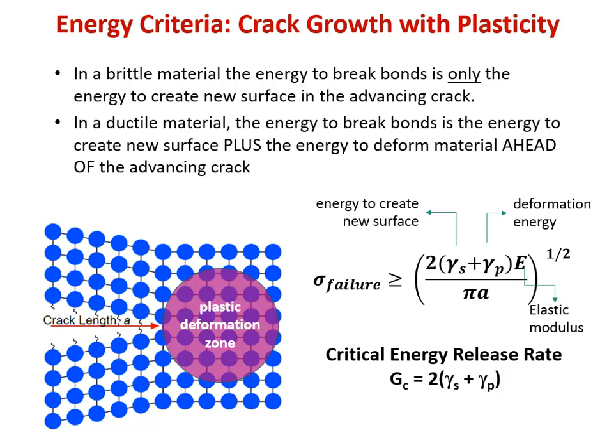So that's moving dislocations or slipping chains a little bit past one another. So that's all those modes of moving plastically within the material. Then we have the elastic modulus over pi times the pre-existing crack length, and all of that in the parentheses being raised to the 1/2. So that's the actual applied stress necessary to fail. So you can think of the main components as being an elastic strain component with our elastic modulus, crack length to the 1/2 power in the denominator, and then our two modes of absorbing energy, creating surfaces and plastic deformation.